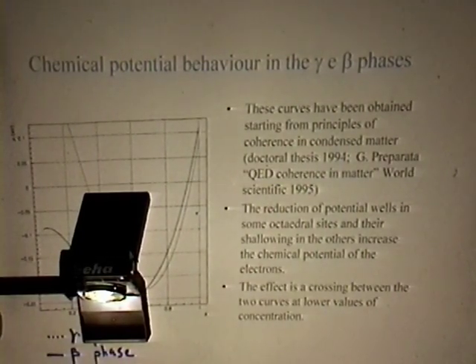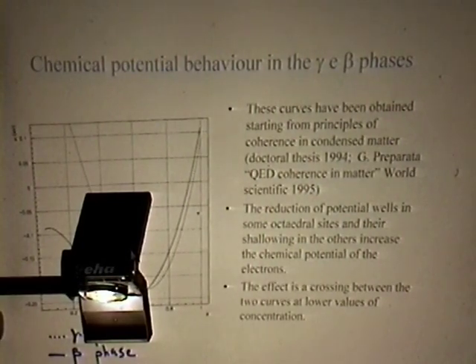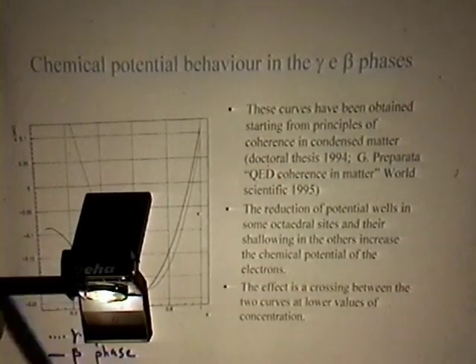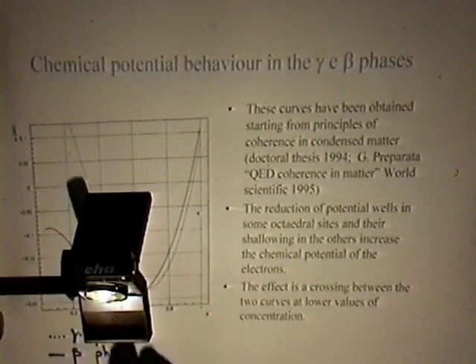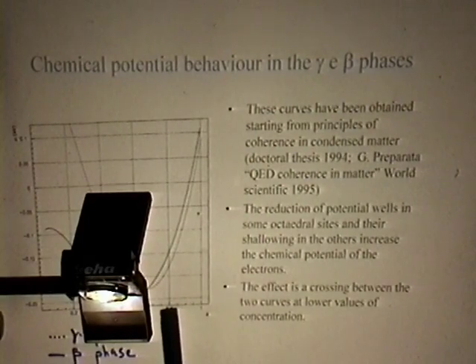Here I want to show you two chemical potential curves that are obtained starting from the principle of coherence in condensed matter. Details can be found in the book of Giuliano Preparata of 1995 and in the doctoral thesis that I can give you if someone is interested. The chemical potential curve was calculated for the beta phase and the gamma phase, a new phase that starts to nucleate when the beta phase is complete. As you can see here, the beta phase curve is lower than the gamma phase, and there is a crossing at 0.65. This corresponds to the maximum of the Baranowski curve, the point when a new gamma phase starts to nucleate.